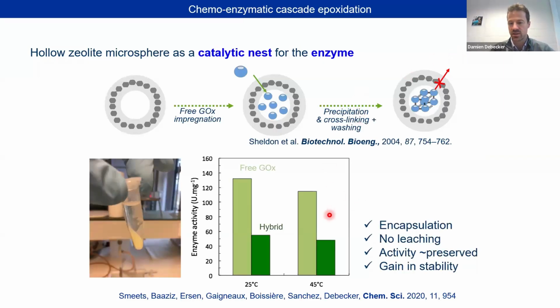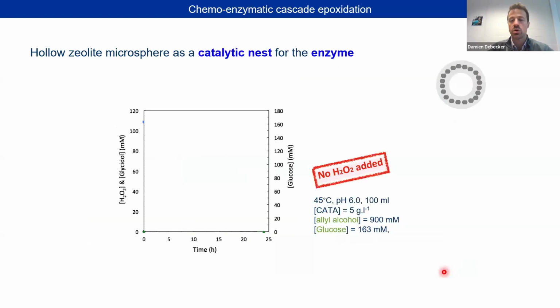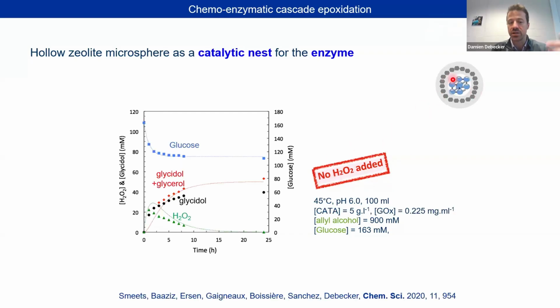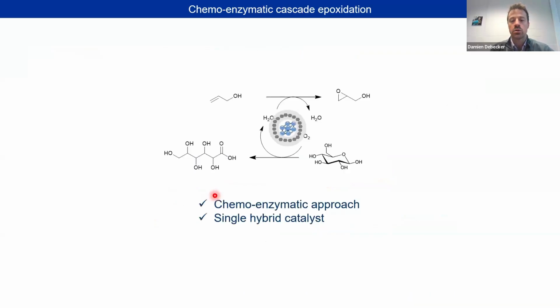We check, of course, that the enzyme does not leach. It is truly encapsulated, and its activity is preserved. A little bit lower, but actually we gain in stability for this enzymatic activity. So if you use just the inorganic cage, and you don't add hydrogen peroxide, nothing will happen. But if you use the hybrid, you see the production of hydrogen peroxide by the enzyme, and then the use of this hydrogen peroxide by the zeolite to produce the epoxide that you wanted to target. So that's a proof of concept for a chemoenzymatic approach.